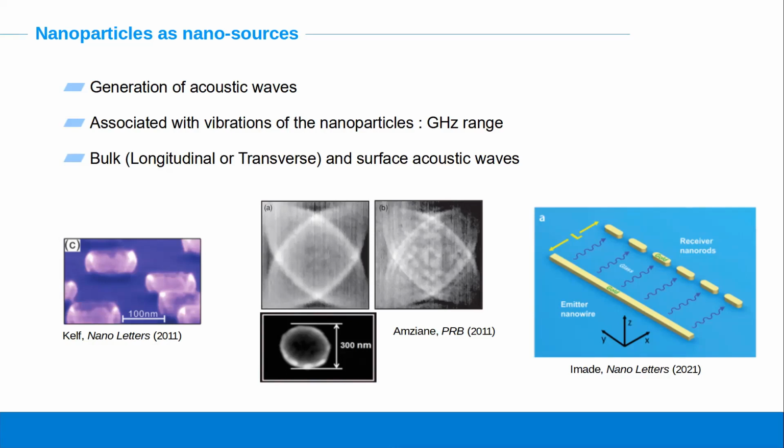And so, for example, Kelf has shown that some nano rings made of gold can generate acoustic waves. Some nanoplates, nanodisks can also generate transverse waves. And more recently, Imade has shown that you can even use nanoparticles, in that case, nanowires, to generate surface acoustic waves.